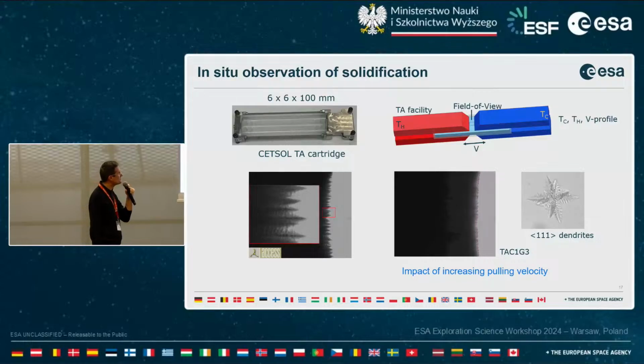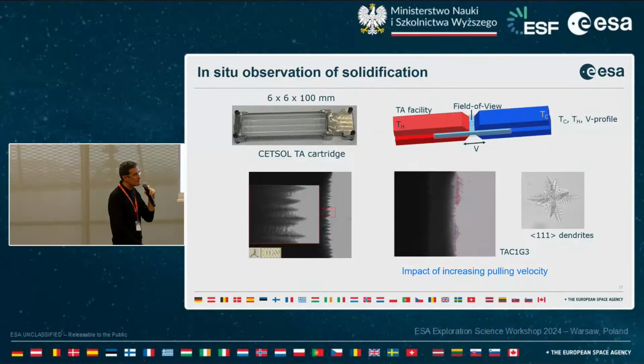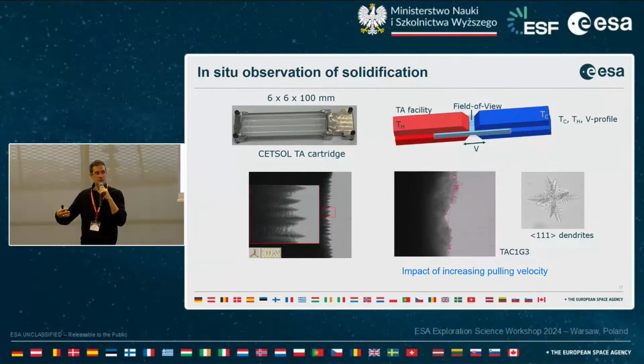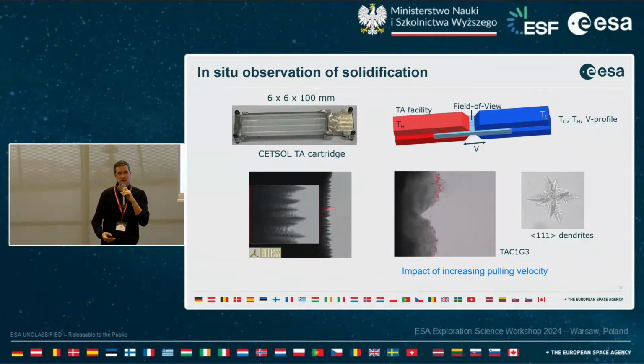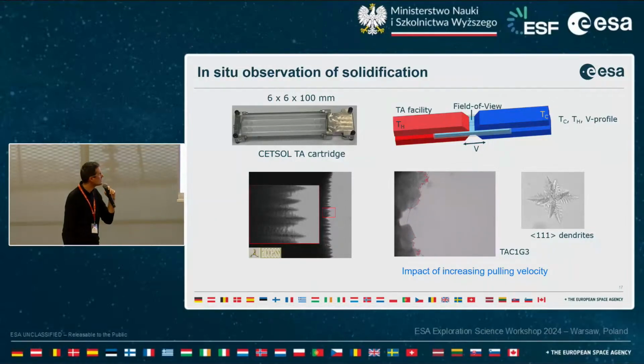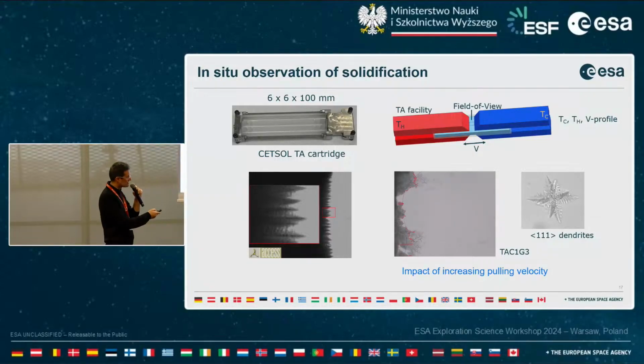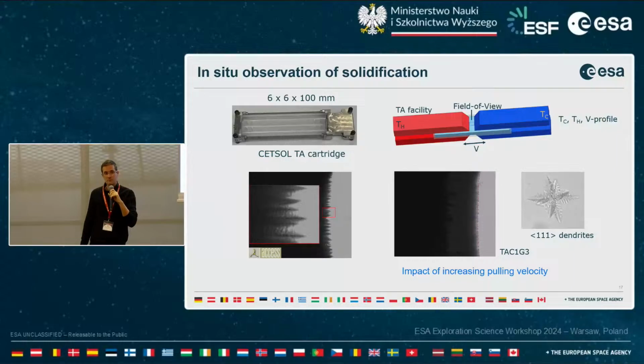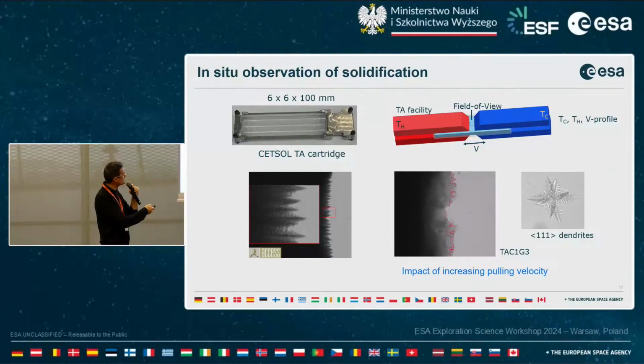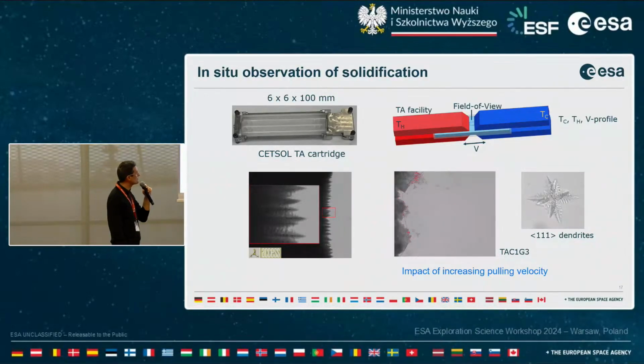And if we look here at this video, it is an illustration of the impact of increasing the pulling velocity. So first we have a columnar structure, and then by increasing the pulling velocity, we trigger the nucleation of the grains that will stop the columnar structure. And then we increase 2 to 3 times the growth velocity, and you can see that the shape of the grain envelopes has been evolving, becoming more and more close to an octahedron shape. So again, you can see here the equiaxed grains growing successively, and then we increase again the growth velocity, and the shape, the envelope of the grain is changing to close to octahedrons.